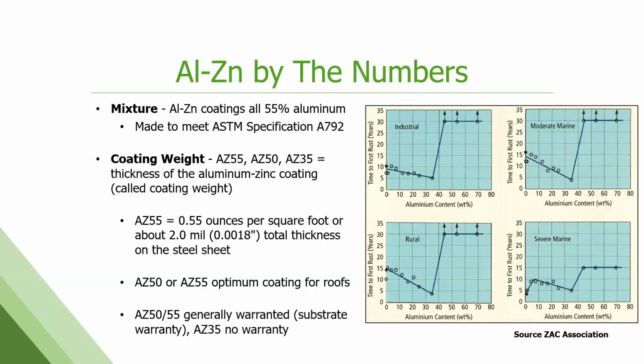If it's AZ35, which is a very, very low coating weight, there is no warranty, and you actually cannot use the Galvalume name or the ZINCALUME trade name for that product because it's unwarranted. But that low coating weight has a place, not for exterior necessarily, but we do see it getting used for interior applications. We see it getting used for appliances, interior electronic housing and casings. So it's good for that. Some low-end rainwater goods too use AZ35 because they don't need the warranty.